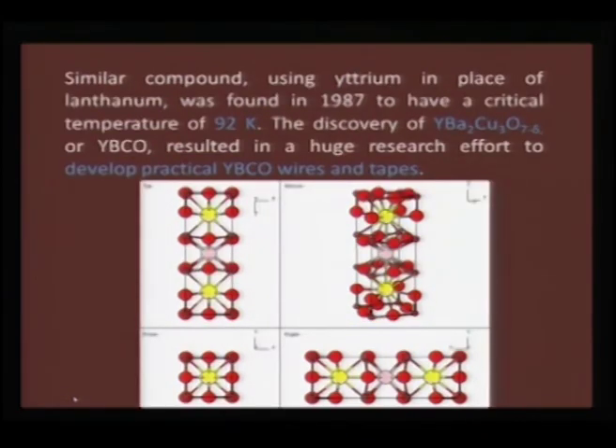Similarly, yttrium barium copper oxide, which actually shows superconductivity at 92 Kelvin, also has a very unique perovskite lattice, and in this lattice you can see yttrium, barium, copper in 1:2:3 proportion. That is why it is called the 1:2:3 compound. You can see here these two are the barium, and in between you have the yttrium, and the copper oxygen planes are in the terminal edges.